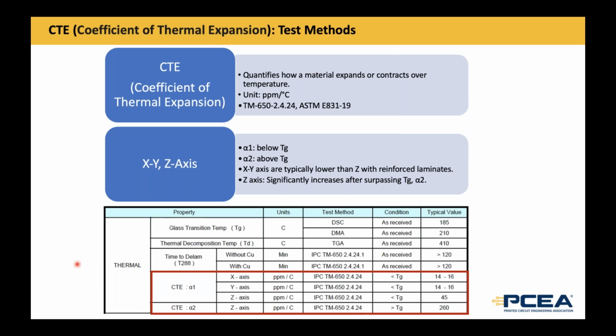Now, as the material heats up, it follows a linear expansion rate until it achieves the glass transition temperature. And as we saw earlier, once it reaches that TG, above TG, the material expands at a different rate. Looking at this example here, it has the XY and the Z axes, and you can see there's alpha 1 and alpha 2. Alpha 1 is below TG and alpha 2 is above TG.